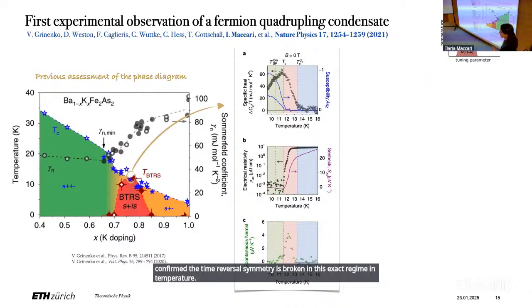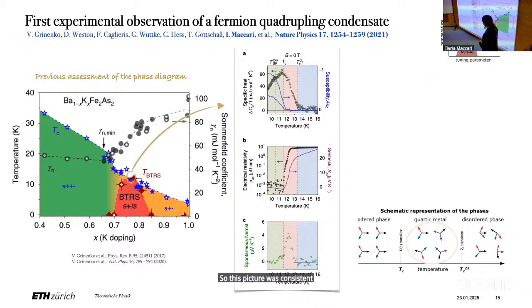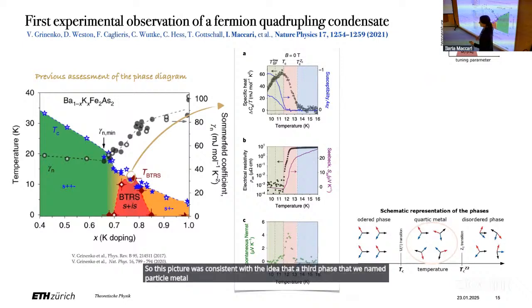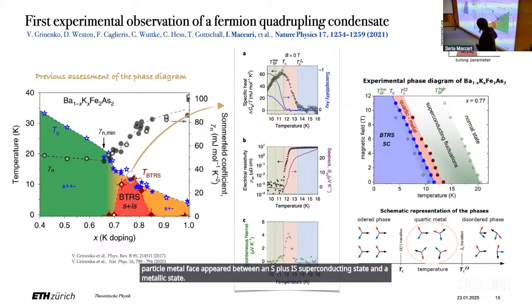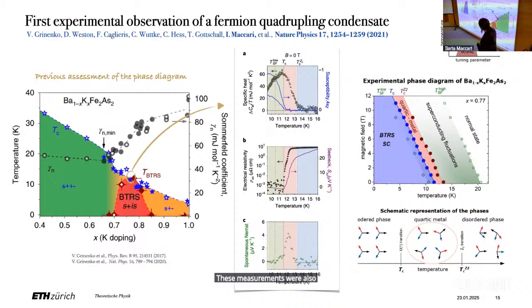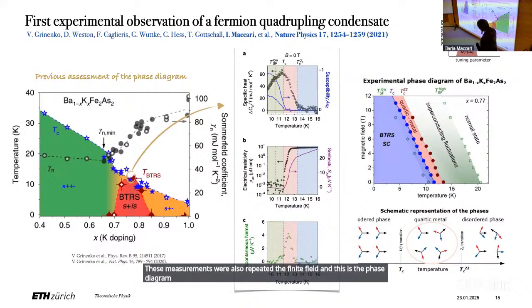So this picture was consistent with the idea that a third phase that we named the quartic metal phase appeared between an s plus is superconducting state and a metallic state. These measurements were also repeated at finite field, and this is the phase diagram as a function of the magnetic field and the temperature.